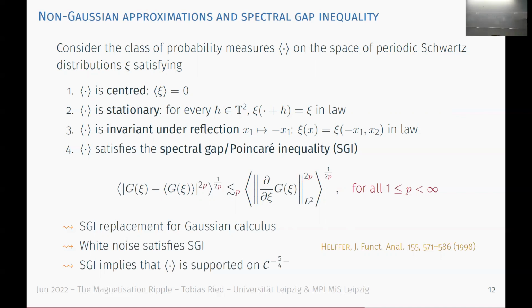A good thing is in this class of noises that I want to consider, white noise is actually contained. And immediately that spectral gap inequality gives you some a priori regularity, namely the spectral gap implies that these measures here are not really measures on Schwartz distributions, but they are concentrated on a much smaller set, namely they're supported on distributions which have some -5/4 minus epsilon Hölder regularity. So if you're not really comfortable with this Hölder scale, maybe you've heard of Besov scales. So that's the natural scale in that problem.